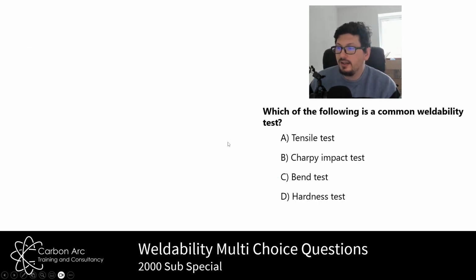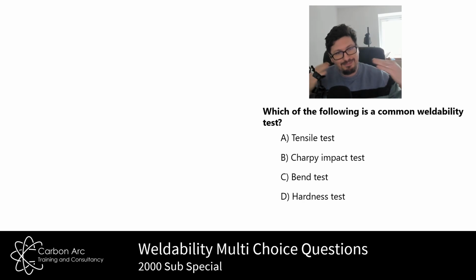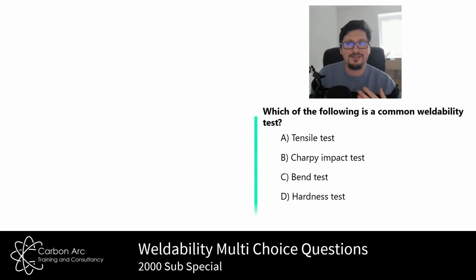Which of the following is a common weldability test? Before I give an answer, yet again, ask the question, what is weldability a measure of? It's the ability to weld it without cracking. Why do we get cracking? Well, we get cracking because we have a high carbon content, which then leads to potentially a martensitic structure, which is more likely to crack. So hardness values go up with a martensitic structure, right? What test is going to find hardness values?